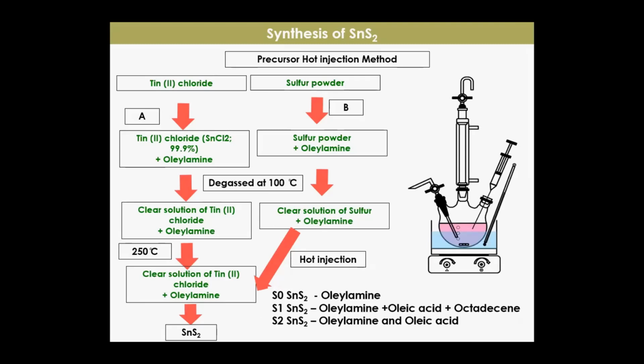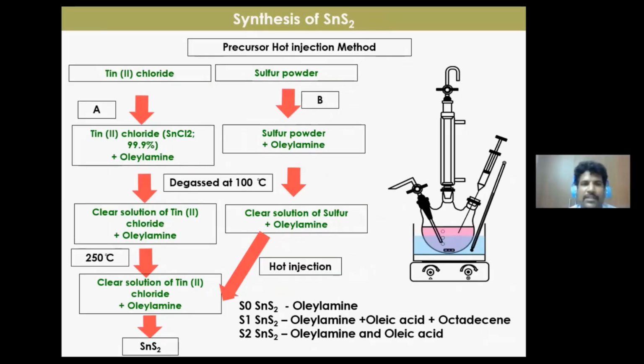First, we start with oleylamine. Oleylamine is taken in two different flasks, flask A and flask B. The precursors, tin(II) chloride and sulfur, were used. We take tin in flask A and sulfur in flask B, dissolved in oleylamine. It was degassed at 100 degrees centigrade, because in our synthesis method oxygen is against our system. If oxygen is there, tin oxide will automatically form. So we wanted to get a single-phase tin disulfide.